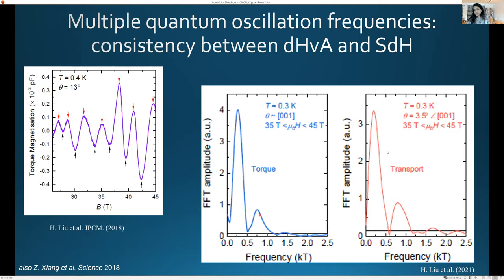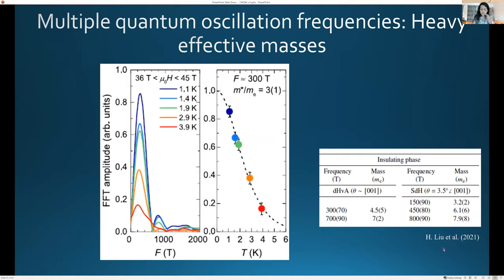And we see similar frequencies in the electrical transport in the insulating state. And we look at it as a function of temperature. The main difference in the case of YbB12 is that the frequencies we see are lower, a few hundred Tesla, and the masses are higher. They're up to about 8 electron masses in the insulating state. This is interesting, and I'll come to this in a moment, because this is reflecting a Fermi surface that doesn't appear to be the large light conduction electron Fermi surface. So maybe there are different origins of the unconventional Fermi surface in these different materials.